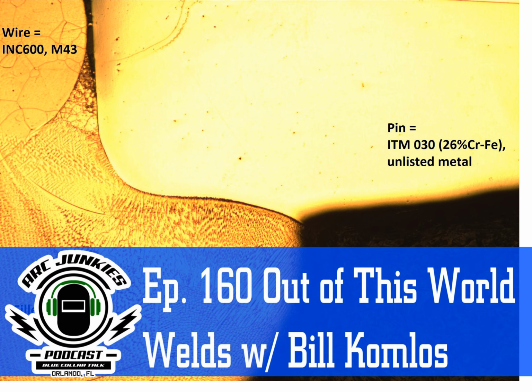But the ferritic won't get that hard, so it's a little easier to work with, but it's still lean in the nickel. Well, magnesium eats nickel, and so they blow out long seams in this 410 stainless, just because the 410S ages, and the grains get big, and they finally just kind of fall apart, because mine equipment's just there to be used because they're on production pounds per hour, right? And so you'll take a $70,000 crucible and you may heat it up to 1,500 degrees is what they're saying. But if you look at Young's modulus in ASME Section D, you've lost more than 80% of your strength at 1,200 degrees. So it's like jelly at 1,500 degrees.